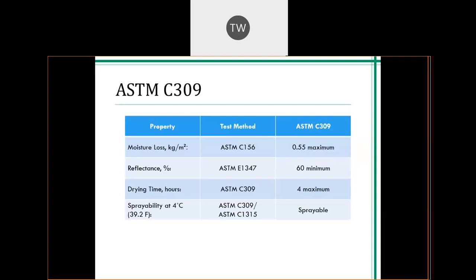As you can see from this chart, there are a number of desirable ASTM performance specifications contained within the ASTM C309 specification that will assist greatly in the placement performance of your specified liquid curing compound. You're going to receive minimal moisture loss, adequate UV reflectance, the correct drying time, and the ease of being able to spray the product in order to put it down quickly, evenly, and easily. So these are the performance requirements that are contained within ASTM C309 specification. ASTM C309 is the older and less restrictive, and typically it applies to curing agents used for highway work or bridge decks.